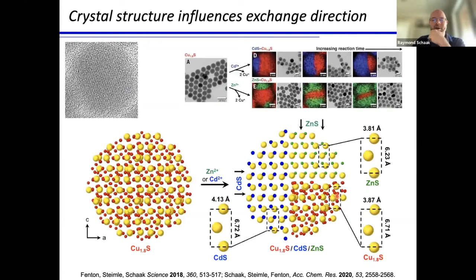And that's that idea of transformative inorganic nanocrystals. But I want to talk a little bit about the role of crystal structure in this, because that's where this becomes, I think, really powerful and exciting. So if we take these nominally spherical copper sulfide particles that we start with, they're single crystalline. So while they're spherical in morphology, their crystal structure gives them asymmetry or anisotropy, for example, just based on where the crystallographic planes are and the differences at the atomic level in the spacings and arrangements of the atoms. So it could look coincidental that for these Janus particles I have these organized to be propagating left to right, where these sandwich ones I have propagating up and down. That's actually by design, and that correlates with the crystallographic features.